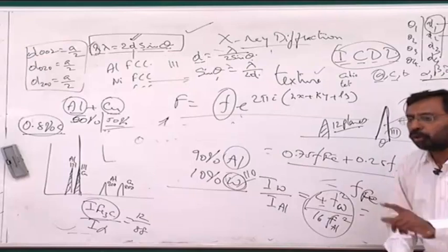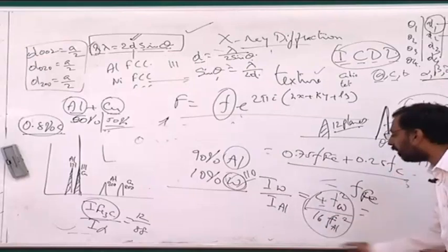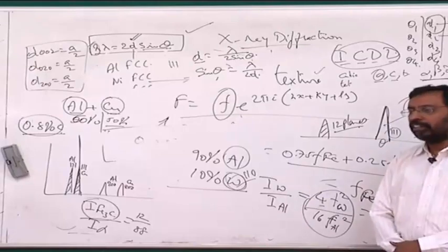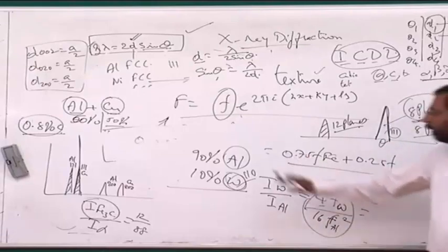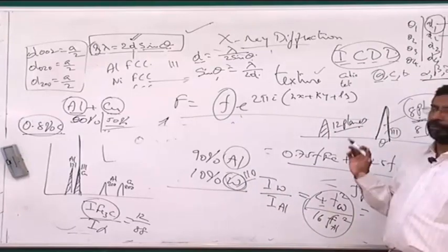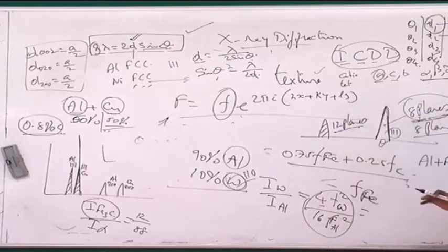It is true only when you can do the corrections for this. There is something called Rietveld analysis in which people do corrections for the actual atomic positions. And when you do the corrections, you will get the correct picture. Until then, you won't. So understanding the limitations of what XRD can do, we can still find out the structures of materials, find out the lattice parameters of the materials and do a lot of things. And we will see what else we can do with XRD in the next class.